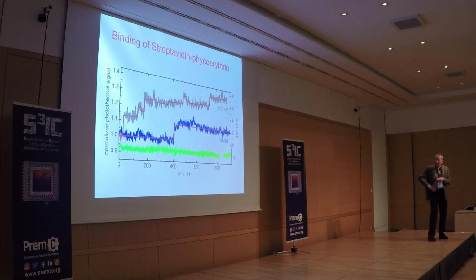So it's shown here. When you do nothing, when there is no streptavidin in the solution, nothing really happens. You have this green trace. At low concentration, you see some occasional events. That's a particularly large one, where the molecule attached to the tip of the particle. And if you increase the concentration, you see more and more of these events happening as a function of time. So this is a sensor, if you like, or a sensing experiment in which you see the landing of single molecules on the surface of the rod one at a time.